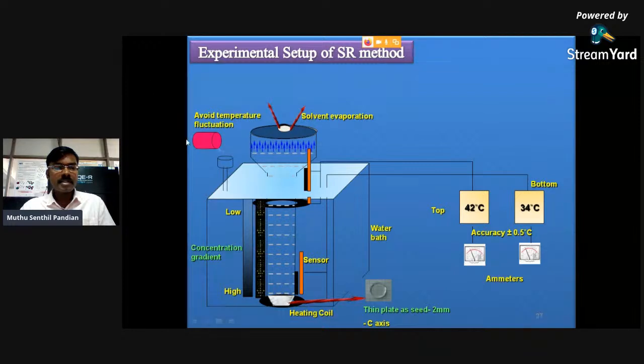To avoid temperature fluctuation from daily variation, water is frequently added in the water bath. We have to maintain the water level in the SR growth sample. Otherwise, the temperature will not be stable. To avoid fungus formation, freshly prepared saturated solution is frequently added in the SR growth sample. We have to do that because with several organic materials, when we grow by the SR method, fungus will form, in the conventional method or the SR method. It is easily formed.